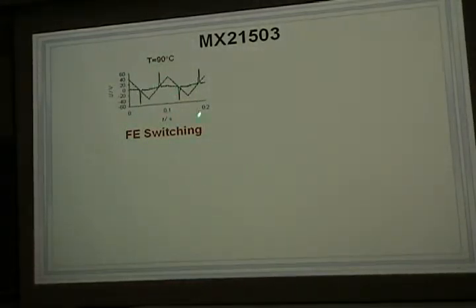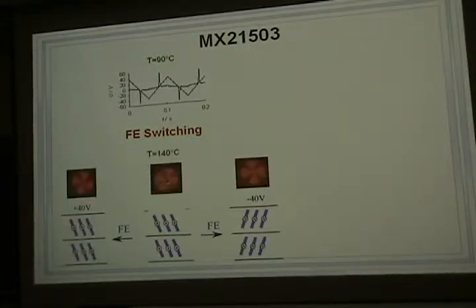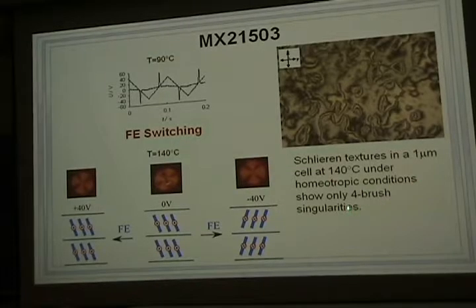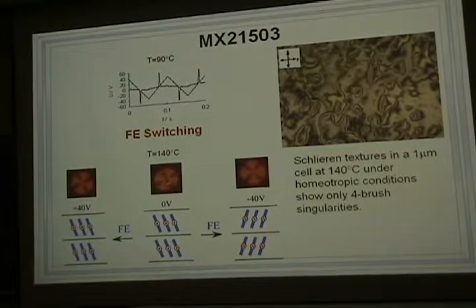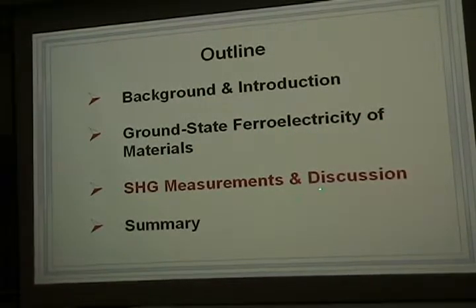The switching current response for this mixture shows only one single peak, indicating ferroelectric switching. This confirms bistable switching for this mixture. The schlieren texture of this mixture under homeotropic conditions shows only four-brush defects. After characterizing the ground state ferroelectricity of this material, we then proceeded to do the SHG measurements.